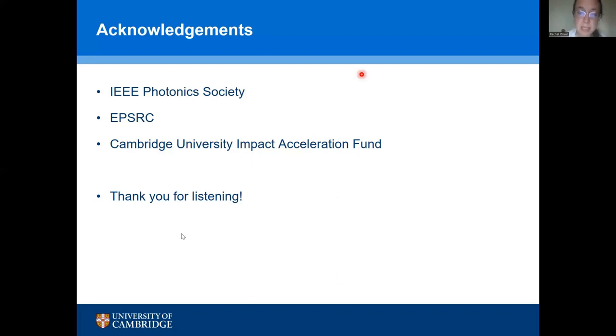Did we perform an annealing on the porous GaN, and how does it affect the DBR and the LED properties? We didn't perform a deliberate anneal, but we did grow structures on top, which means we held the DBR at temperature. And you have to be quite careful about how you start the growth. If you hold it at temperature too long without starting the growth, you start to see the pores getting bigger and the porous layers starting to run into one another. And that degrades the properties of the DBR.